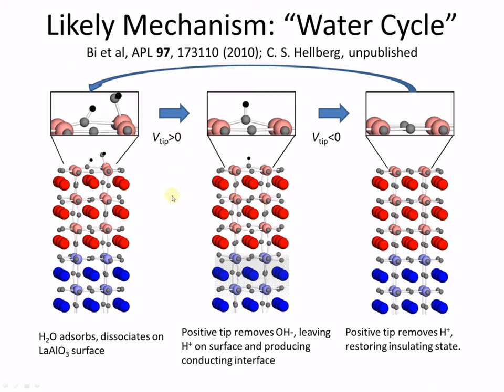This is, of course, a very simplified model, but we do know from experiments that were published recently that if you do not have water, then you cannot write structures, but you can erase them under vacuum or under dry air conditions. And that's consistent with this simple picture.